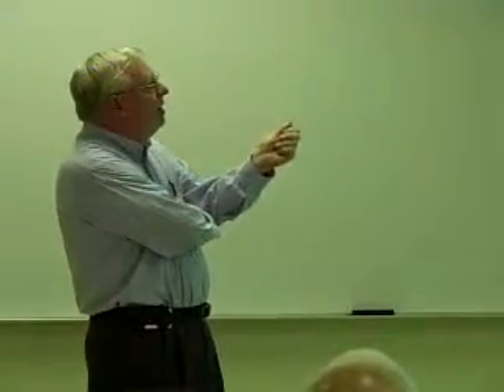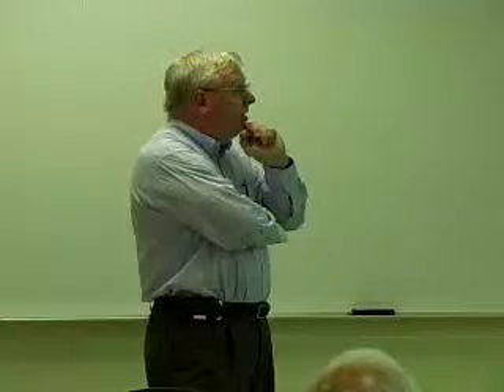Okay, tin whiskers I think are one of the neat things. But tin whisker, it turns out the lead in this lead tin solder greatly inhibited, didn't completely eliminate, but really inhibited tin whisker growth. At the end of this talk, we're going to talk a little bit about tin whiskers. The lead suppressed the copper-tin reaction, that's the intermetallic formation. And like I said, we have 60-plus years of experience with it. So we're going to talk now about this SAC 305.